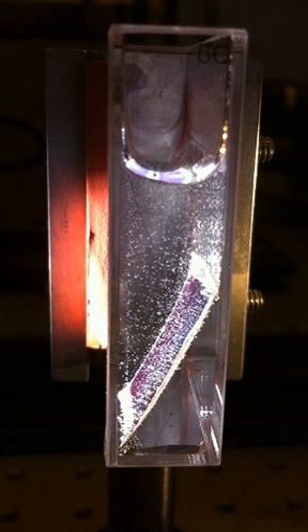During 2009, F. Del Valle and K. Doman showed the effect of the thermal treatment in a closed atmosphere using Cd1-xZnxS photocatalysts. Cd1-xZnxS solid solution reports high activity in hydrogen production from water splitting under sunlight irradiation. A mixed heterogeneous molecular approach by researchers at the University of California, Santa Cruz, during 2010, using both nitrogen-doped and cadmium-selenide quantum dots sensitized titanium dioxide nanoparticles and nanowires, also yielded photoproduced hydrogen.